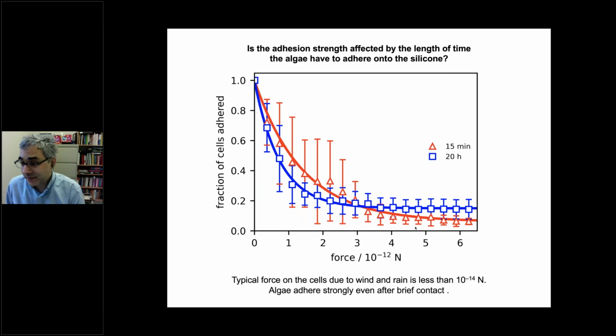And this is very interesting for the field studies, because you can see that even a very brief exposure to algae causes them to stick just as strongly as if they had a chance to actually secrete more substances and be stronger adhered, which is not the case. And the other interesting thing here is if you look at the values of the force along the horizontal axis of my plot, and you compare this with the typical force that's exerted by environmental conditions like wind and rain, it shows you that even minutes of algae adhesion results in cells which are stuck onto the silicone surface more strongly than can be removed just by things like wind and rain force. And this really goes to show why it's such a strong problem of fouling of insulators by algae.